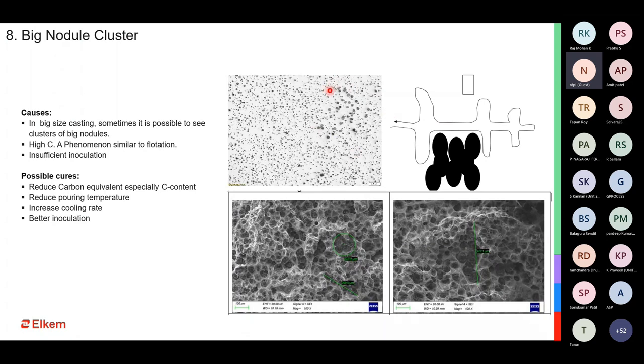It is a phenomenon which is very similar to flotation, but here it does not get sufficient time or pathway to go to the top or float to the top, and it gets trapped between the dendritic arms or the secondary dendritic arms. So thereby it gets segregated in some of the parts within the casting. So you can see it here. You can see it here. You can see it here. So this is again a large casting problem. It happens mostly in the heavy section castings.